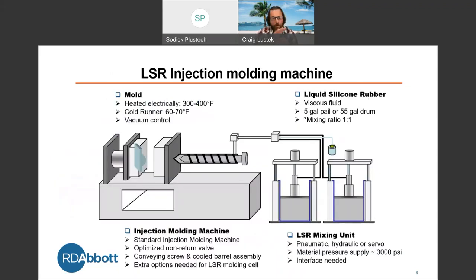When we look at the overall spec of the setup, we're looking at our mold, which in the industry is mostly electrically heated, anywhere from 300 to 400 degrees Fahrenheit. There can be a wide range of temperatures you're utilizing there depending on the type of parts you're running. Cold runner, we want to stop the curing happening. So we want to put a chilled system onto our static mixer, screw, and barrel. So we want a cold runner anywhere from 60 to 70 degrees Fahrenheit. And again, vacuum control for that.